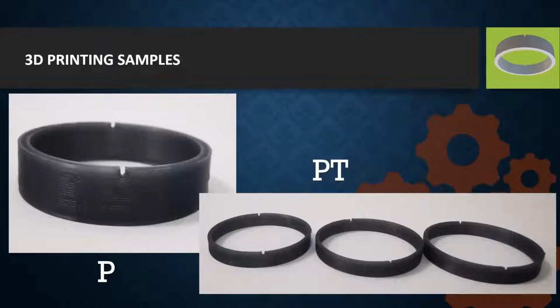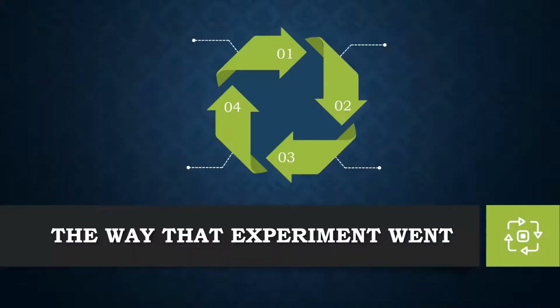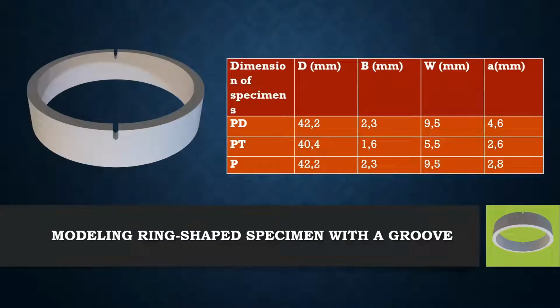That was for the test specimen made with available additive technologies. In particular, testing of ring-shaped specimens with a groove and a crack printed on an FDM printer made of PLA material. And this is how the experiment went. The first step in performing the experiment was to model a PRNT pipe ring notched tension specimen with a groove. 3 types of samples were prepared, of which the PT model has a shorter length compared to the others, and the PD model has a larger groove compared to the other 2 types of models.